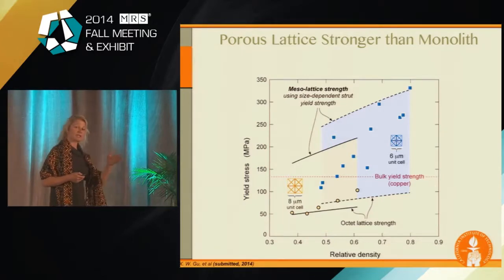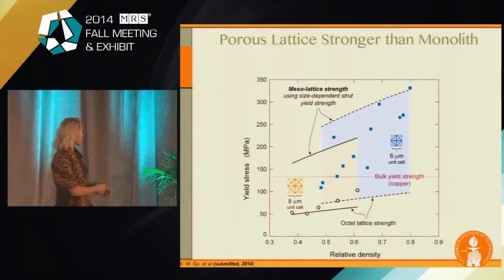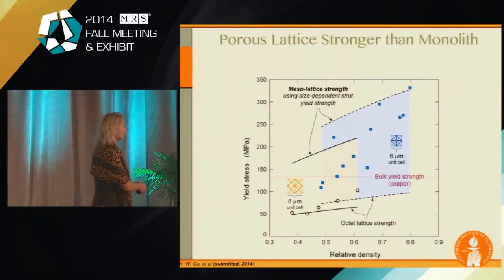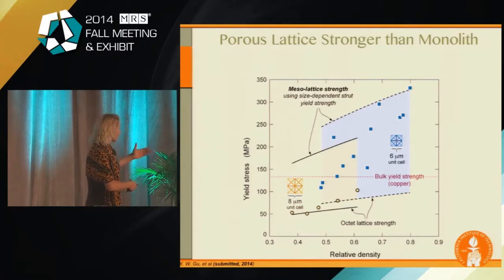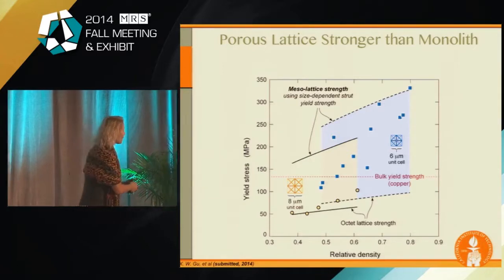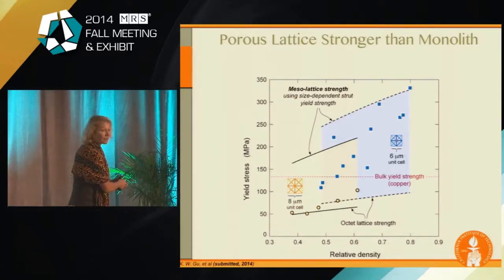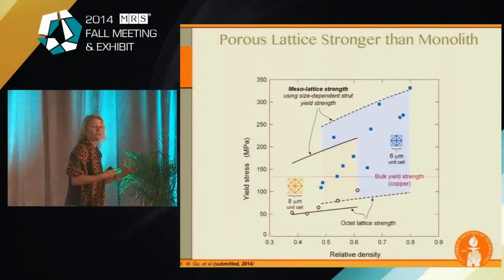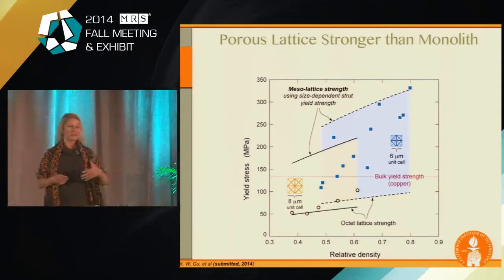And now she kept the relative density the same, which means that at about 50% relative density, the 8-micron struts will be wider than the 6-micron ones, right? Because she effectively scales it up. So what you see already is that the 8-micron is weaker than the 6-micron one. So basically, going smaller always buys you strength, even though that implies that you're taking the material out. It's very counterintuitive, but it's real.